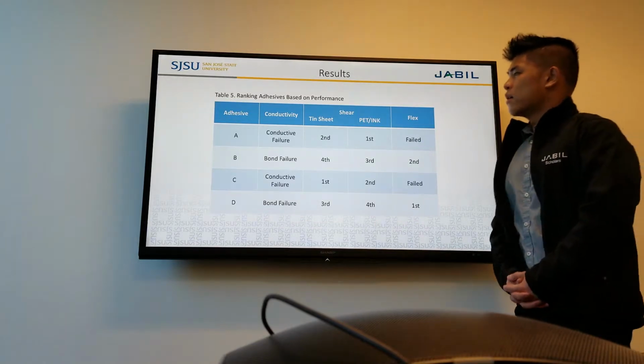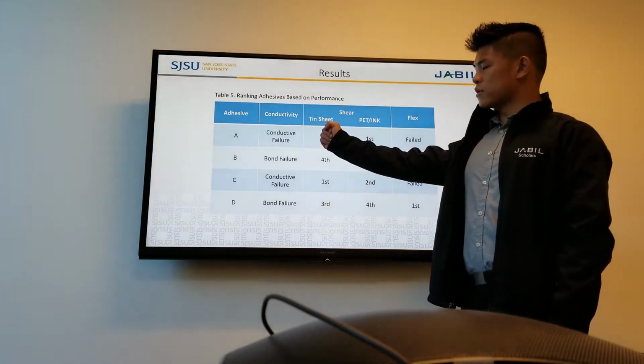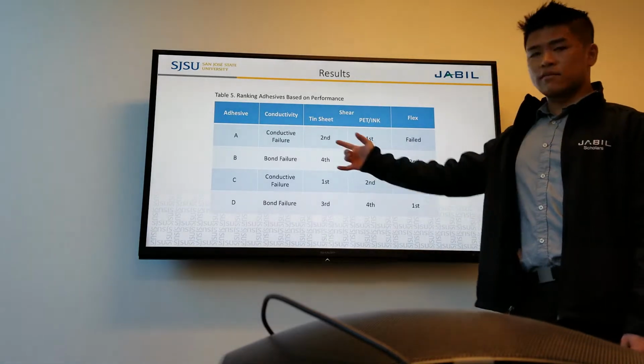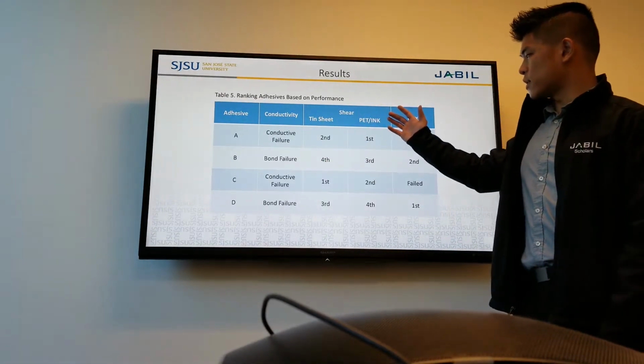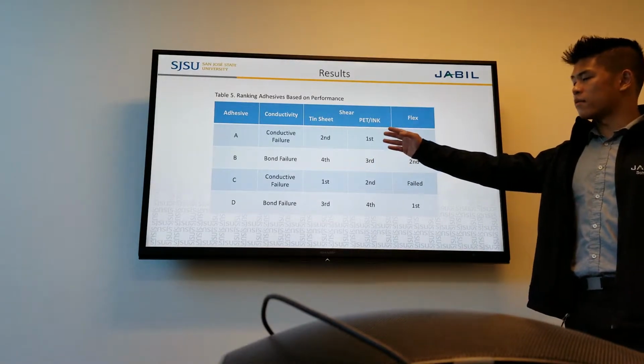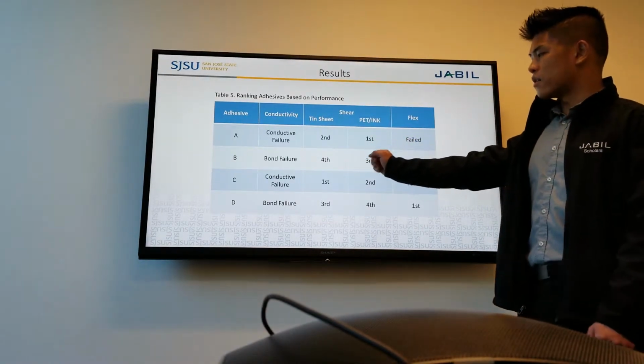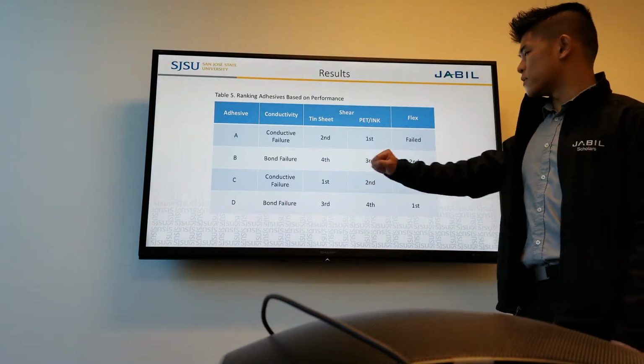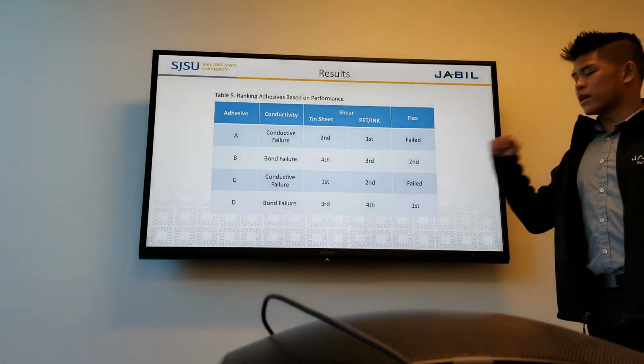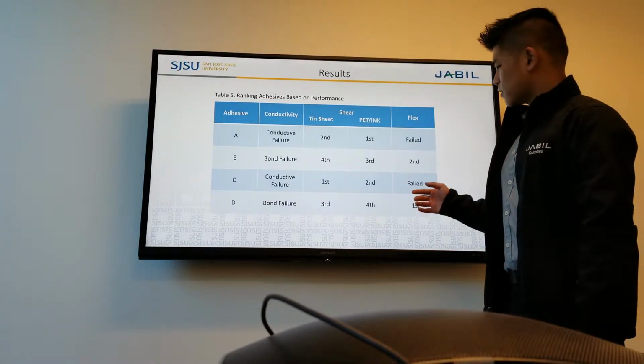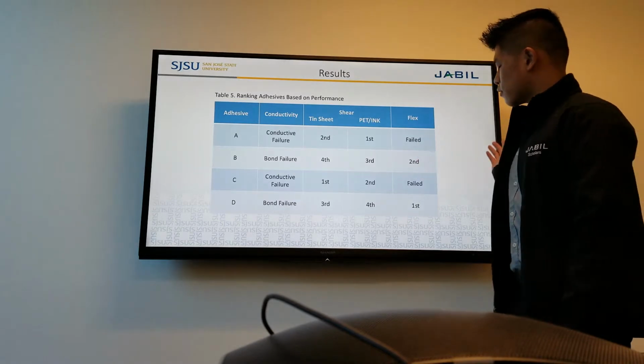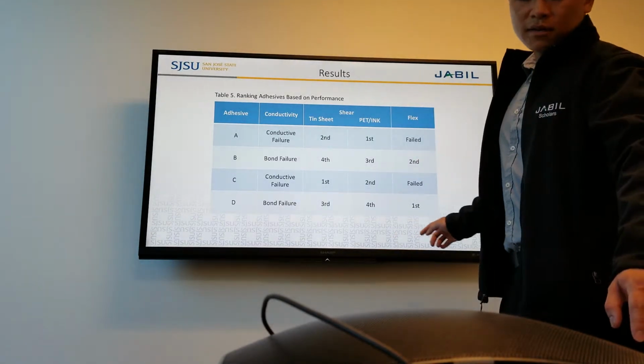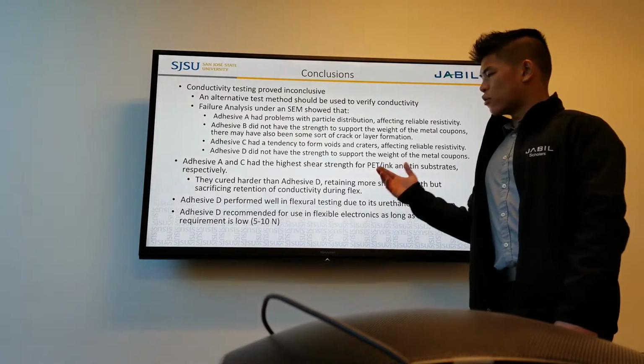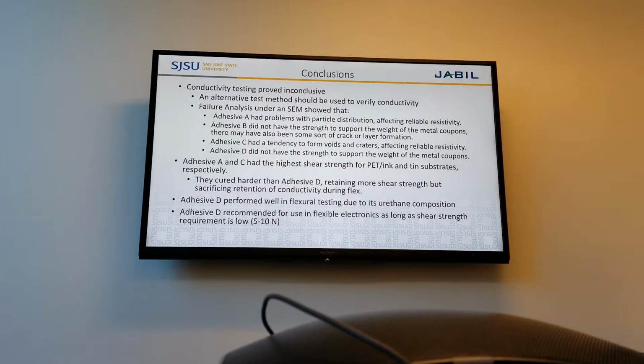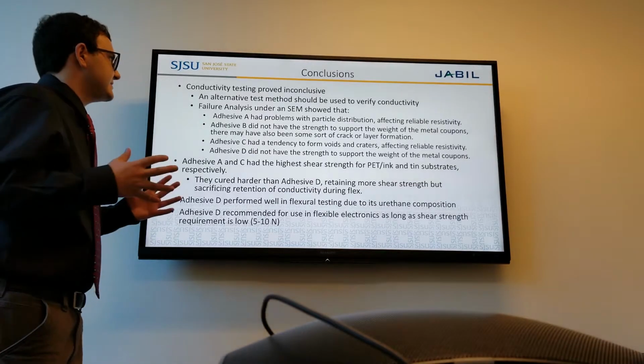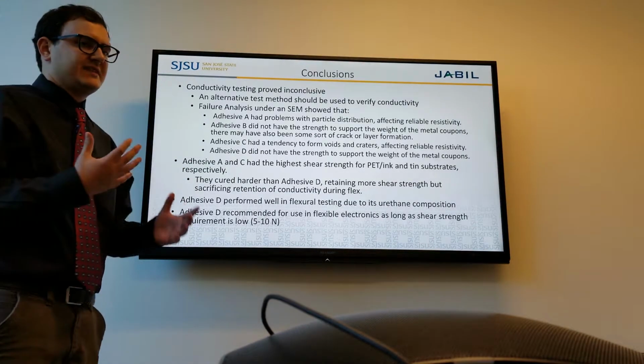For our total results, conductivity testing, as we said before, was inconclusive. A and C had a conductive failure, and then B and D had a bond failure. In the shear strength test, the best adhesive for PET ink was Adhesive A, and then the best adhesive for tin sheet was Adhesive C. And then the flex test only had 2 to really pass the test, Adhesive D and B, even though B failed ultimately at the end. So we would recommend Adhesive D as our overall recommendation. So for the conductivity test, it proved inconclusive. So what we'd like to do in future work is establish some sort of alternative test method.